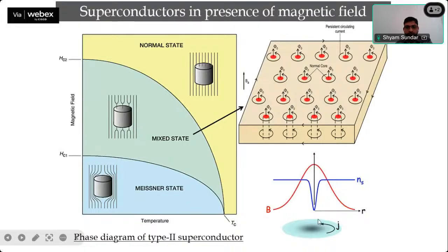Similarly, the superfluid density, which is the density of the superconducting electrons, which we call the Cooper pairs, goes to zero because the core is normal. And as you go away from this core, the superconducting electrons increase. So if you can see the distribution of this magnetic field in your material, you can tell about the penetration depth into the superconductor, which is related to the superconducting electron density.